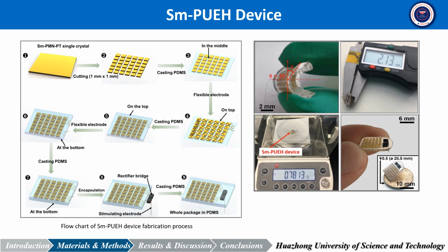The Sm-PUEH device, as you can see, is flexible and miniature. The bending angle of our device can be greater than 30 degrees. This device is 13.5 mm long, 9.6 mm wide, and 2.1 mm thick. The total weight of our device is only 0.78 gram.